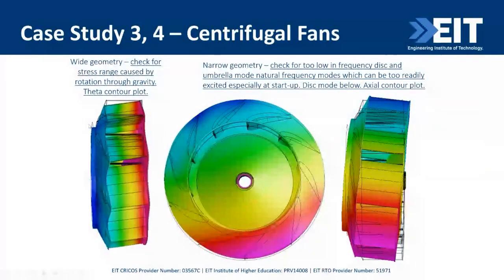This is what I'm saying about rotation through gravity. Ignore the contour plot there. That was inadvertently plotted as a theta. So, hoop stress, theta angle plot, forget about that. The deformed shape shows you that at top dead center, the blade to back plate angle is closing up, so compression. At bottom dead center, it's opening out, so tension. And it's that tension to compression which is making the stress range again under gravity. So, years ago, people didn't worry about this, looking at that fatigue case. It is critical, particularly for wide impellers.